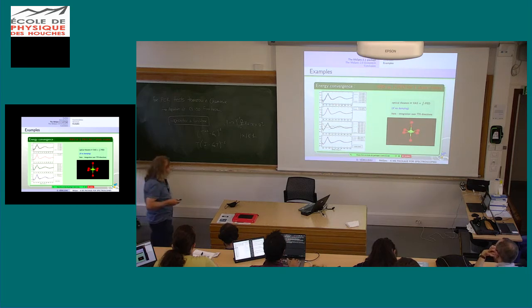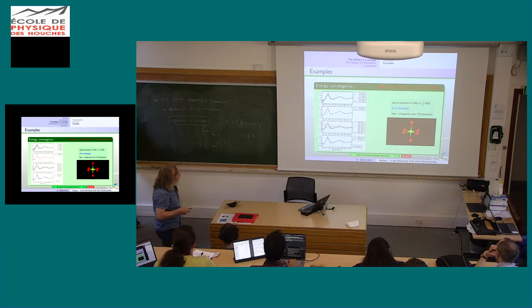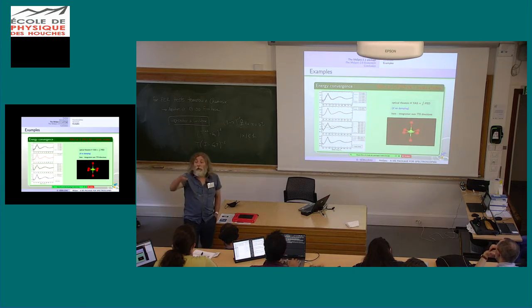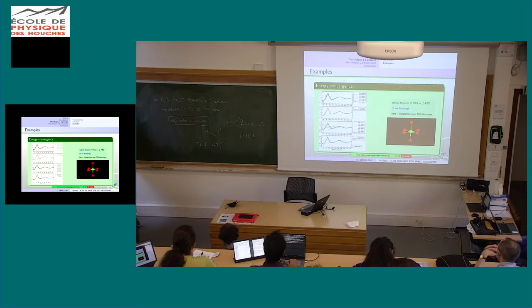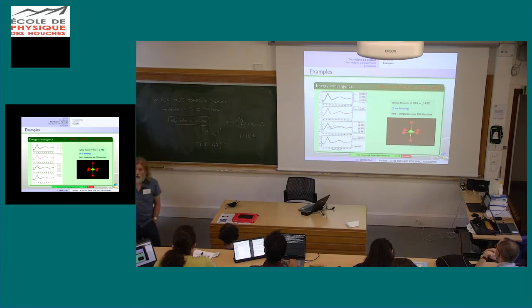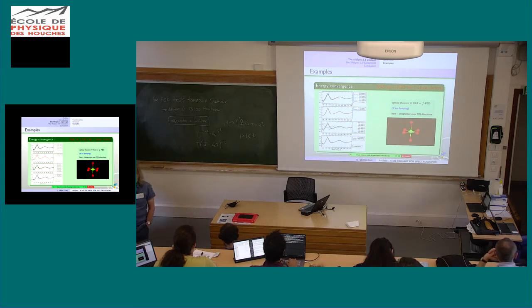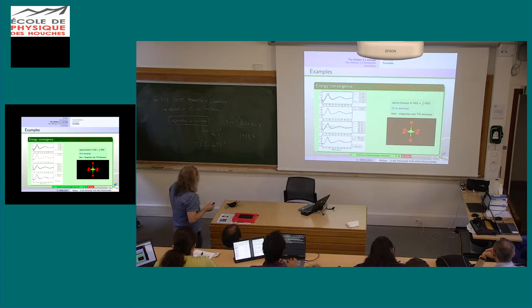Here is an example first with a simple seven-atom structure — it's only EXAFS. To go back to the question from a few days ago: this is the part above 50–60 eV where you've got these oscillations, and if you take a Fourier transform you get your peaks that coincide with the positions of the shells of atoms around. Here you see the different scattering orders for the calculation of X-ray absorption with MSPEC, and the comparison of order seven with matrix inversion. That's excellent.